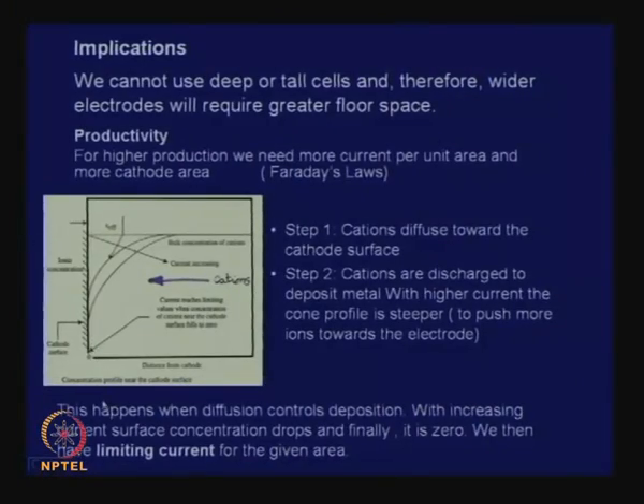This becomes the limiting current, and limiting current divided by the area of the electrode becomes limiting current density. So, in any cell, your first goal will be to increase the surface area. Having increased the surface area, your goal will be to increase the current, so that you can produce more metal. As you increase the current, how will the current be sustained? Because it is a diffusion controlled process, there will be more gradient. But beyond a certain level of current, the surface concentration of metal ions falls to 0. There is nothing left, and therefore, it cannot go down any further. That is the limiting current density.